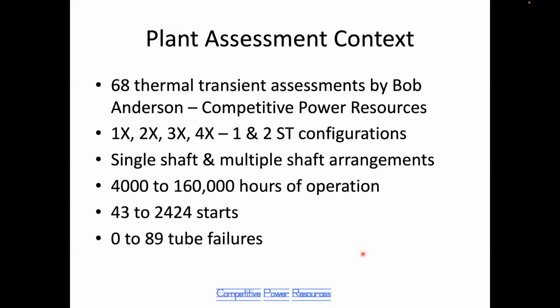These thermal transient surveys have been performed on 1x1 combined cycle units, 2x1, 3x1, 4x1, and combinations of HRSGs with 2 steam turbines. We've done single shaft, multi-shaft arrangements. These plants range from 4,000 hours to 160,000 hours of operation at the time the survey was performed. And they range from 43 to 2,424 starts at the time it was performed. This group of 68 plants, some of them have had no tube failures. And there's one that has had 89 tube failures, if you can believe that.